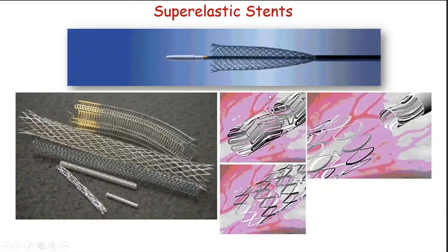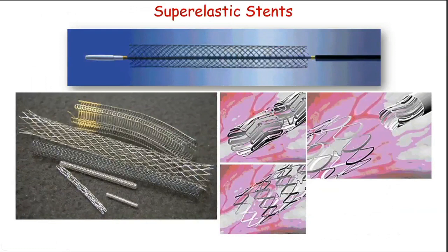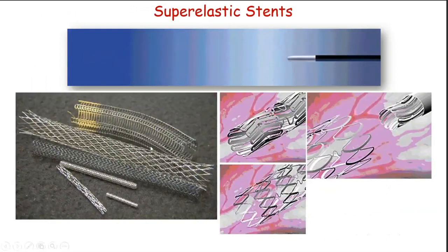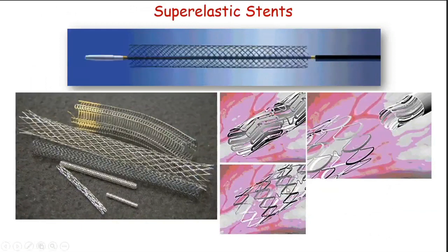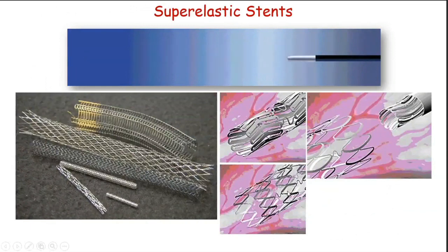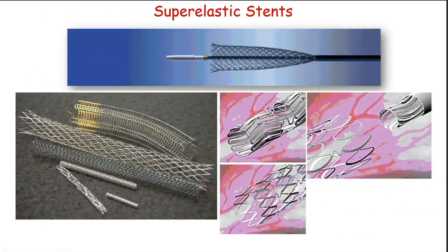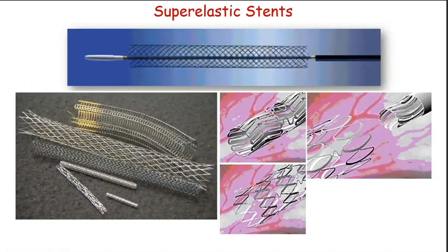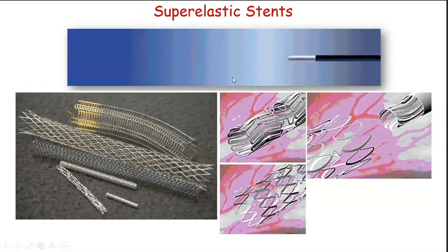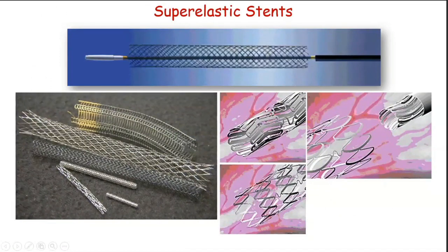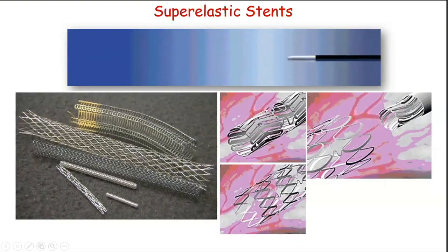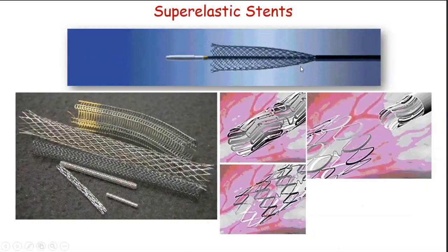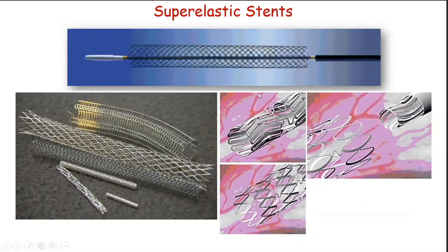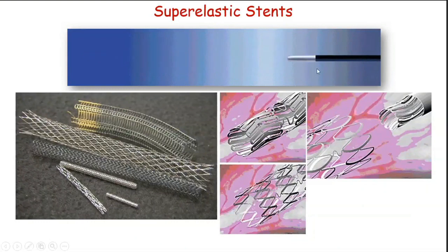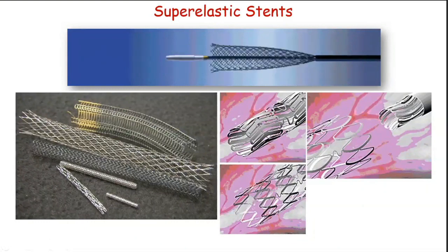Now, this is the most outstanding example of superelasticity. In this, the nickel titanium superelastic alloy is a material which has got the austenite stable at room temperature. Which means to say that I can change this temperature. That's what comes with alloying, that you can alloy nickel titanium with ternary additions and change this transformation temperature. We'll talk about it in a couple of slides later. So what is done is that you make another alloy of nickel titanium, say nickel titanium copper or chromium, and bring the transformation temperature such that it's austenite at room temperature. And now it is superelastic.